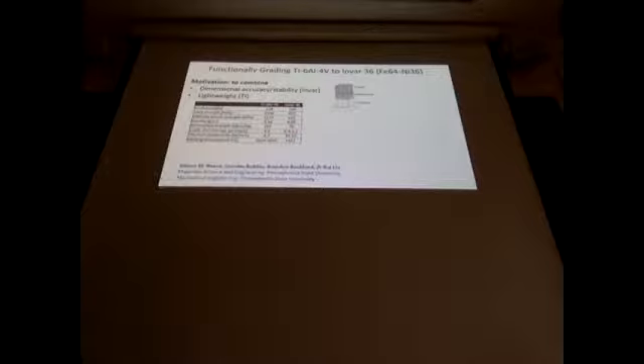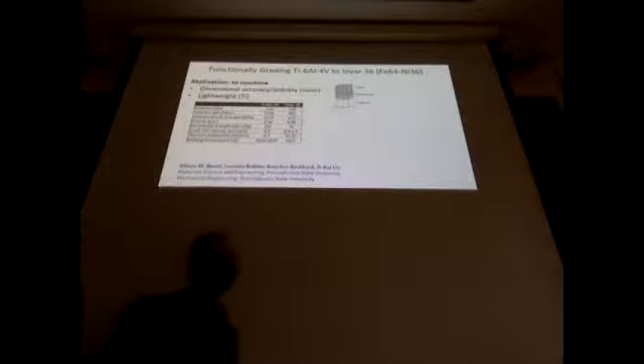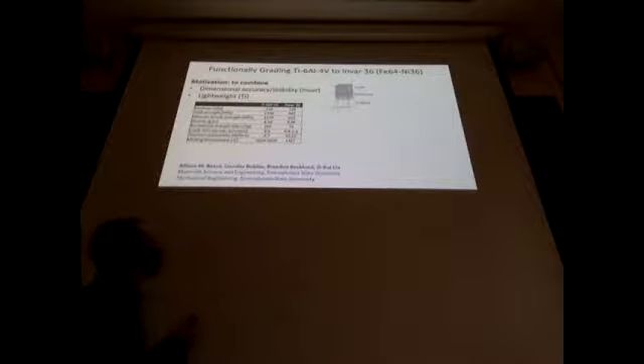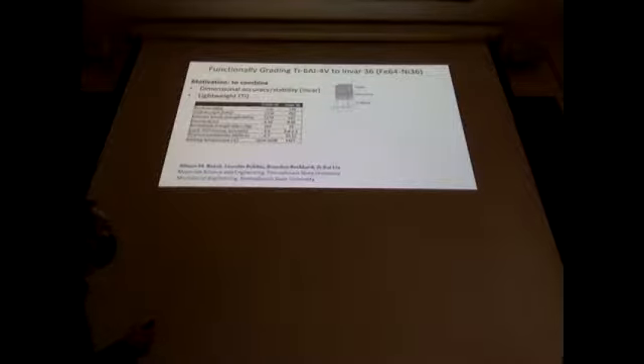So she tried to do Ti-64 to Invar. The benefit of Invar is it shows very little thermal expansion. It's almost zero. And then the titanium has a little bit, but Invar is very heavy. So let's say we can combine the fact that we can get a component that shows very little thermal expansion in one area, but we have the lightweight strength of the titanium on the other area. And that's the benefit of going after this.